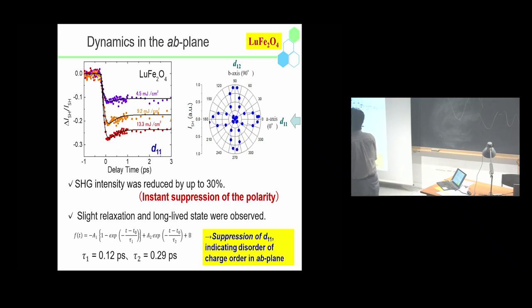By using this formula, and also considering the pulse width of the laser light, we extracted the decay times. The first decay time is 0.12 picosecond, and the second decay time is about 0.3 picosecond. Anyway, we observe the huge suppression of the d11 component in SHG. This indicates a disorder of the charge order in the ab plane. But this is a quite reasonable conclusion that we had expected.